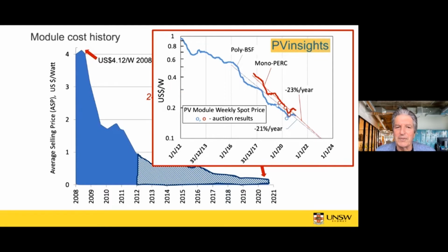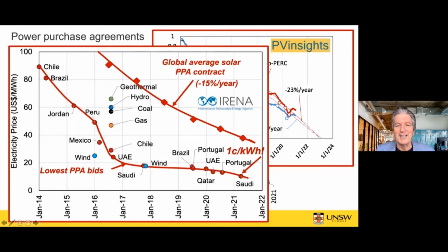So on this semi-logarithmic plot, the blue curve there, approximately can be fitted by a straight line. So that's what that is a sign of, is exponential decrease in costs. And if you plot the most recent region of that cost reduction, fit a straight line to it, you get something like 20% a year cost reduction compounded. So that's a situation we're in. Even though the previous curves, it looks like things are flattening out a bit, they're not really. The costs are still going down very rapidly.